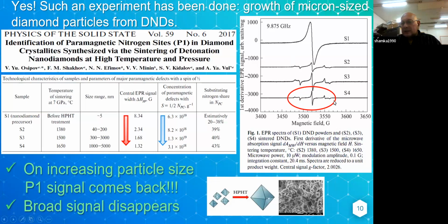And again, they see that this broad central line disappears and the typical P1 signal appears. It means that something happens inside which synthesizes P1 defects again, or in detonation nanodiamonds, P1 defects were there from the beginning, but they were not observable. And only when you go from small particles to larger particles, you can observe this signal. On increasing particle size, the P1 signal comes back, and this broad signal disappears.